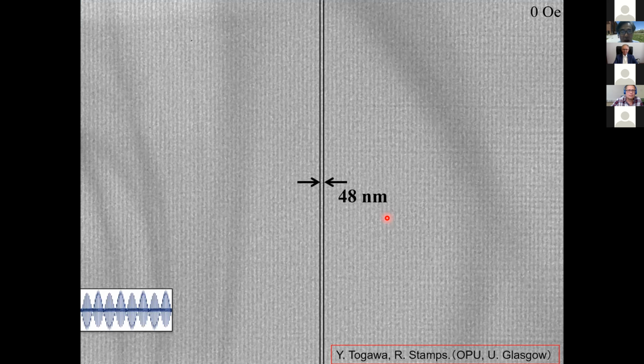This is a Lorentz STEM image of this sample. The c-axis is horizontal. And here a 48 nanometer pitch corresponds to the pitch of the helix.